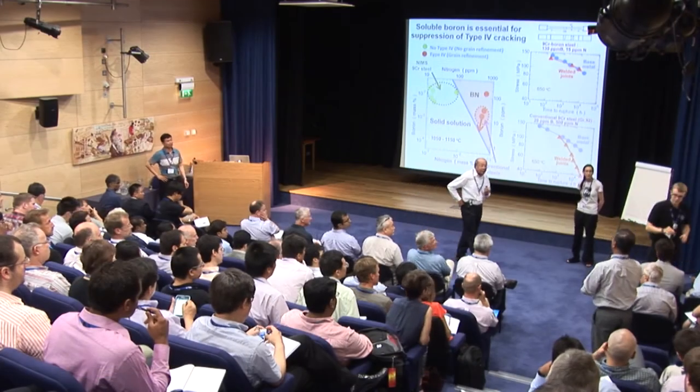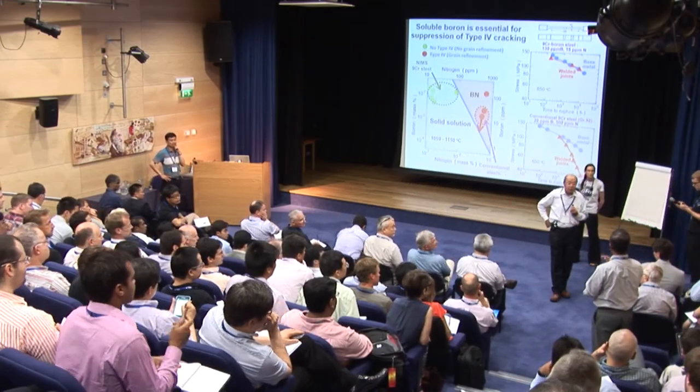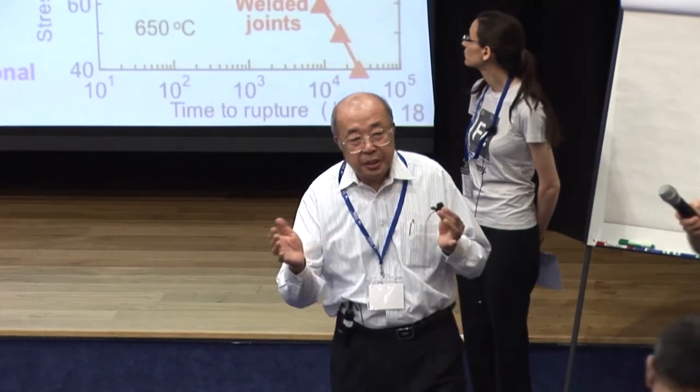Okay. Professor Abe, one of the things which went by, which may be good for a discussion, is that you observed a displacive transformation of ferrite to austenite. That'll be interesting to discuss. How did you come to that conclusion? It'll be very helpful. Thank you. So it's a competition. We think it's a competition of diffusive transformation. Our idea is boron retards diffusive alpha-gamma transformation. But from an energetic point of view, it needs transformation. So the problem is by diffusion or by shear. It's something like a maraging steel.